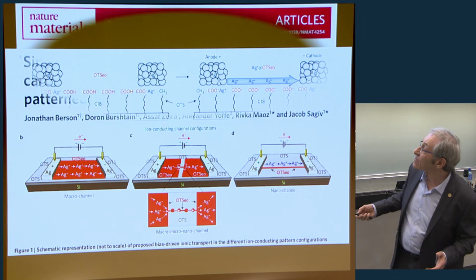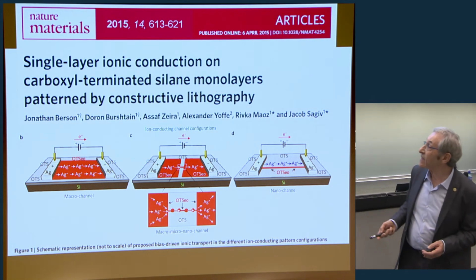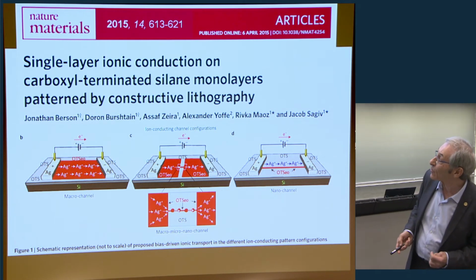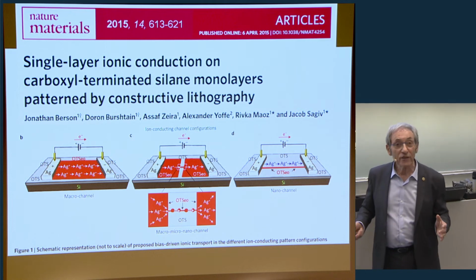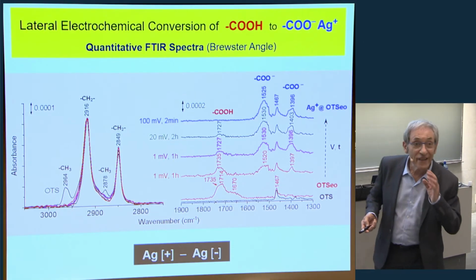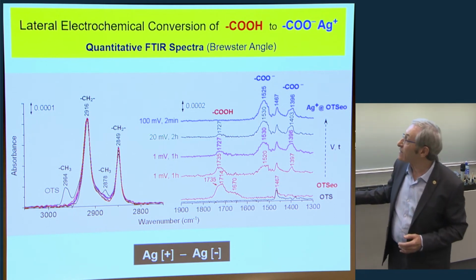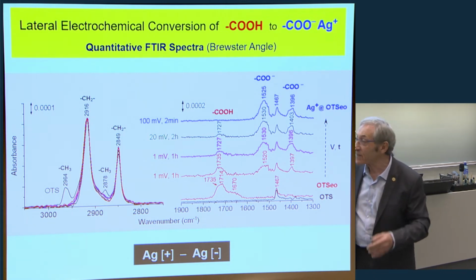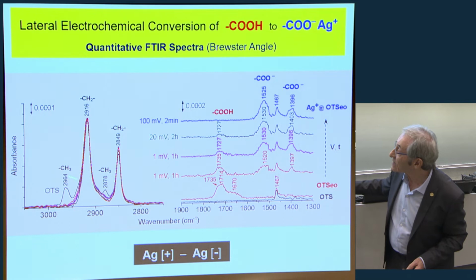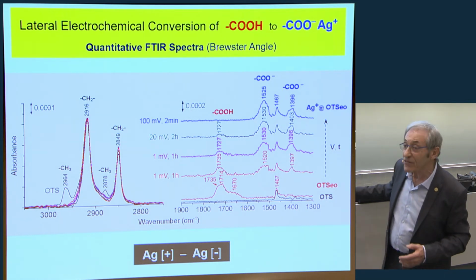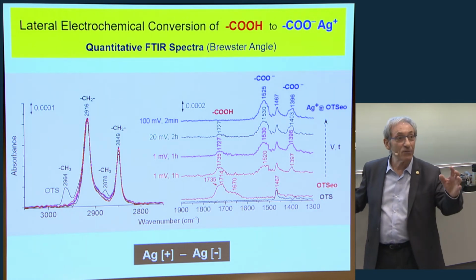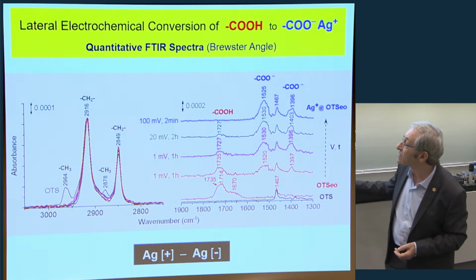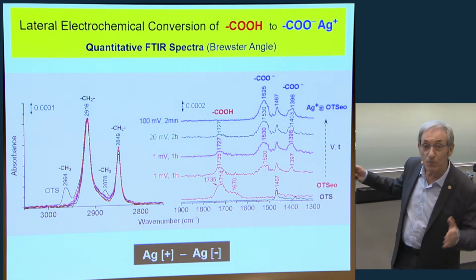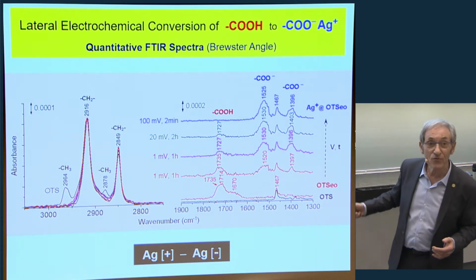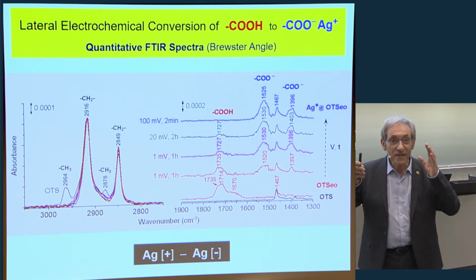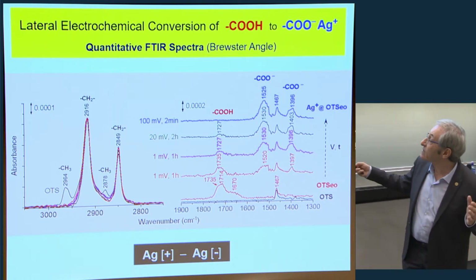And in 2015, we actually published this, single-layer ionic conduction in carboxyl terminated silane monolayers patterned by constructive lithography. And with infrared spectroscopy, we could show directly the patterning process. You see this, in this region you are looking at the CH stretchings. And this is the methyl. And if this is the original OTS, there is nothing here. After the patterning, this disappears quantitatively because the methyl is converted to carboxylic acid, and this is the carboxylic acid features. When you start applying bias, this disappears, and this feature appears, which is silver carboxylate. So we can see directly that we replace protons, and this is a lateral process.